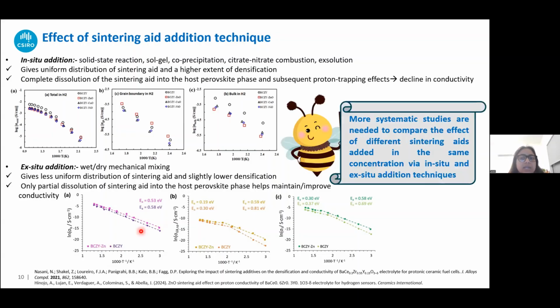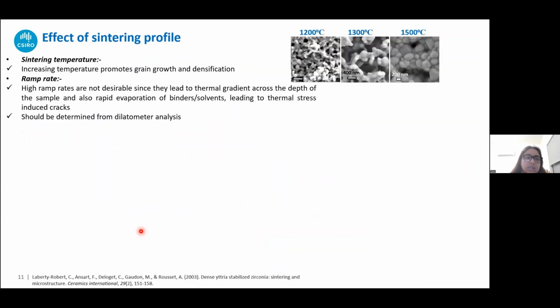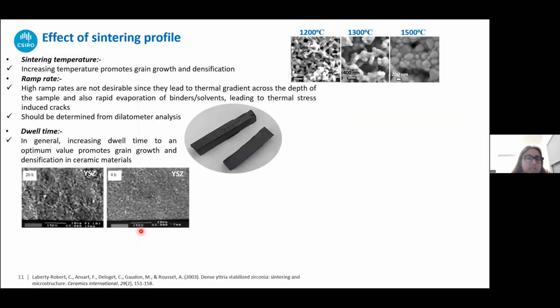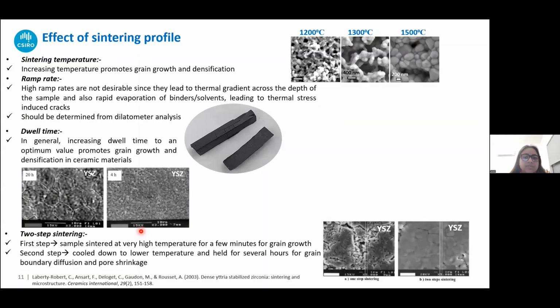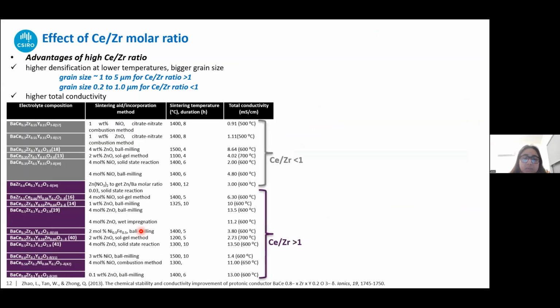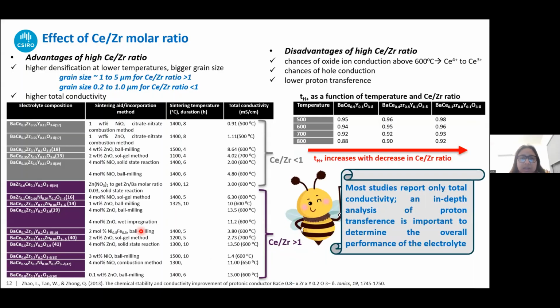So here also, I would say that more systematic studies are needed to compare the effect of different sintering aids when they are added in identical concentrations via both in situ and ex situ addition techniques, because it is possible that there could be a certain regime, like maybe in the low concentration regime the in situ addition is working better, however in the higher regime it is not. Then again, the sintering profile is also very important because, depending on the sintering profile, you can get cracks and all these things, which is not very favorable. And the effect of the cerium zirconium molar ratio, as I already mentioned. So I won't go through all the things because we are running out of time.